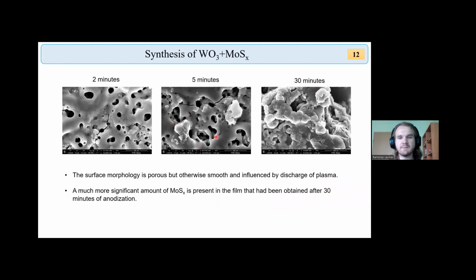The surface morphology of these samples is fairly unique because it is not nanoporous, or it is not very ordered, because the anodization is carried out in such a way that some plasma discharge occurs. And as the plasma discharge occurs, this creates certain pores that can reach towards the base metal, the tungsten, and sometimes they do, sometimes they don't. What is important to us is that we notice that when the material has been synthesized by anodization for 2 minutes, a fairly thin film is formed with small nanopores. However, when the process takes 30 minutes, then much more molybdenum sulfide is deposited, which has also been shown by EDX.